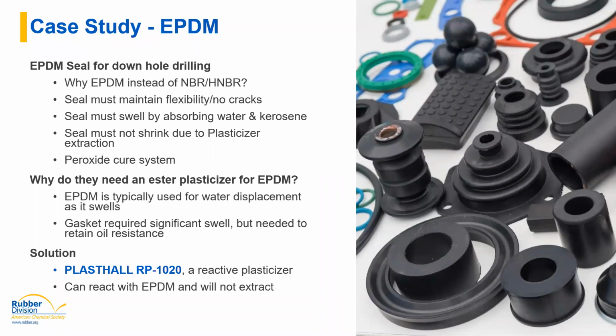This was a difficult application to find a solution for, but we were actually able to offer them a reactive plasticizer, something that has some unsaturation in the backbone of the plasticizer. Now, this was only effective because they were using a peroxide cure system. These types of plasticizers have not been shown to be very reactive in sulfur cure, but in peroxide cure, the peroxide can actually cross-link the plasticizer into the polymer network, giving an even better resistance to any kind of extraction or migration because they've been chemically bonded to the actual elastomer.